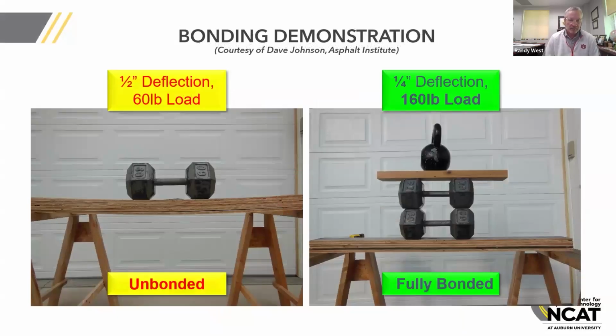So on the left is where those plywood strips are not bonded. There's nothing between them, no glue or anything like that. He put a 60-pound weight on there and he got a 1/2 inch deflection. The right side shows if those layers are glued, they're fully bonded. And in this picture, you can see he added 160 pounds and had only a quarter inch, half the deflection. So I think this is just an excellent demonstration of what we're trying to achieve with tack coats and bonding of pavement layers.